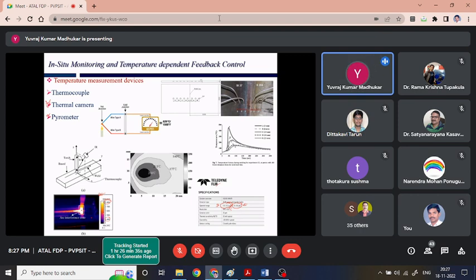So for reading this temperature, which one should we go for? The peak temperature, or the average temperature; we can also set the peak temperature we are getting from the camera. But if we set the peak temperature, possibly in the case of a wire arc process, this peak temperature is not the melt pool temperature. It is possibly the temperature of the arc just below the electrode, and in the case of TIG and plasma, possibly this peak temperature represents the temperature of the electrode itself. Since it works on a broader spectrum, it is always going to give us the relative thermal distribution around the melt pool.